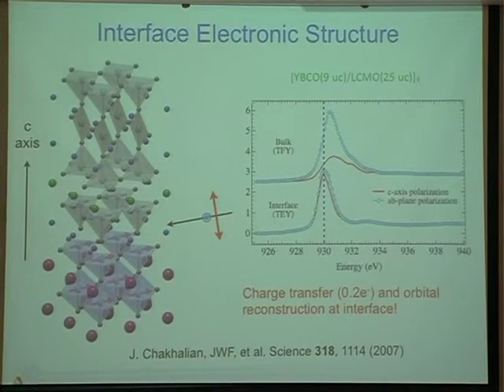But when we did this, we were looking at very, very thick structures. And so lately, we've been going back and revisiting this problem because we knew there was something going on at the interface, but we really didn't know how far. How far does this penetrate in the layer? Is this a very abrupt phenomenon? Does it continue for many layers? And also, where is the superconductivity? We knew if we had a thick layer, even though we saw this phenomenon at the interface, the layer in the middle was still superconducting. And so the question is, where do these crossovers happen?